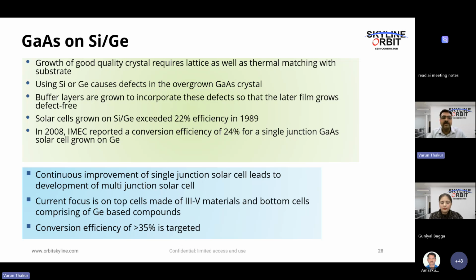So on silicon and germanium, the solar cells which were grown in 1989 have exceeded 22% efficiency. And in 2008, IMEC reported a conversion efficiency of 24% for the single junction gallium arsenide. So keep in mind that it is much higher now compared to what was grown earlier. So research is still going on, and now they are targeting a conversion efficiency of more than 35%. So III-V materials are currently in focus, and continuous improvement is going on, and we are targeting to grow a multi-junction solar cell with an efficiency of more than 35%.